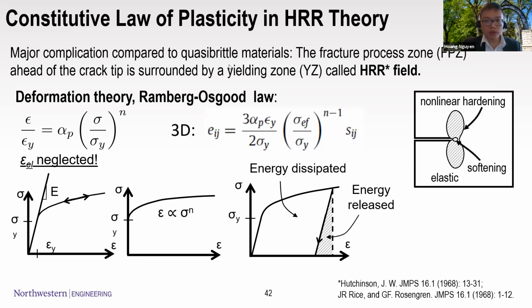So how do we come up with the correct theory for the scaling of the ductile materials here? First of all, we take advantage of the HRR theory. That is the abbreviation of the names of the founders, Hutchinson, Rice, and Rosengren. Based on the deformation theory of plasticity, it means that they use the total strain as the plastic strain, and this strain presumably follows the nonlinear elastic regime, in which case you don't have any unloading happening at the yielding zone or the HRR field. And the Ramberg-Osgood law assumes that the strain is a power law of the stress, and hence it results in the corresponding power of the strain and the stress here.